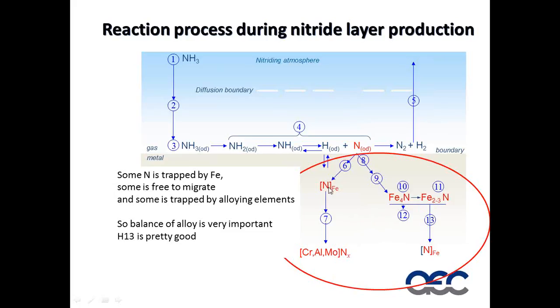Some of the nitrogen is just dissolved in the steel. It doesn't react with anything. And some of the nitrogen reacts with chromium, aluminium, molybdenum, and other alloying elements in our steel. Now this can get very interesting because now we start talking about what alloying elements we need to get the best nitriding response. I can tell you I did some tests in the late 90s with some steel from Böhler, and it had aluminium in it. It was killed with 0.5% or 1% aluminium in the steel. It nitrided as hard as I've ever seen anything nitride.